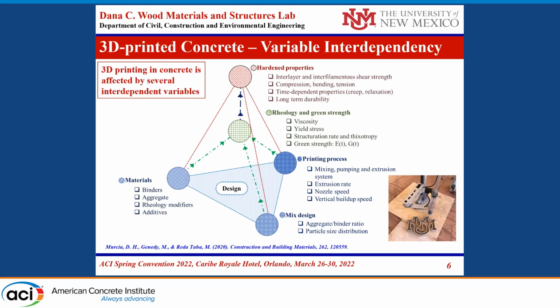And the base basically is these three key variables: the materials, including the binders you are using, the aggregate you are using, the rheology modifiers, the additives; the printing process, including mixing, pumping, and the extrusion system, the rate, the nozzle speed, the vertical buildup; and then the mix design we are doing, including different aggregate-binder ratio and particle size distributions. So all of those together contribute to the middle stage, which is the rheology and the green strength.